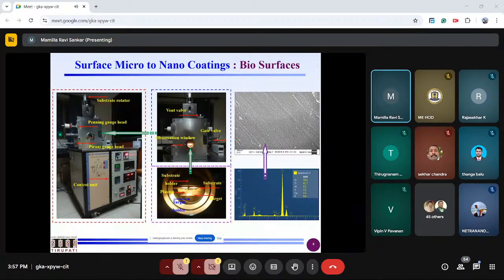The second thing, in coating systems, we have three systems. One is a pulsating DC system, and the other is RF magnetron sputtering. In RF magnetron sputtering, we have a single target one and a multiple target one. For example, if you want to coat multiple materials and functionally graded materials and so on, you can do that. Whatever you are seeing here is RF magnetron sputtering, where you have a substrate and a target. The target will be bombarded, and you can have multiple target materials also.